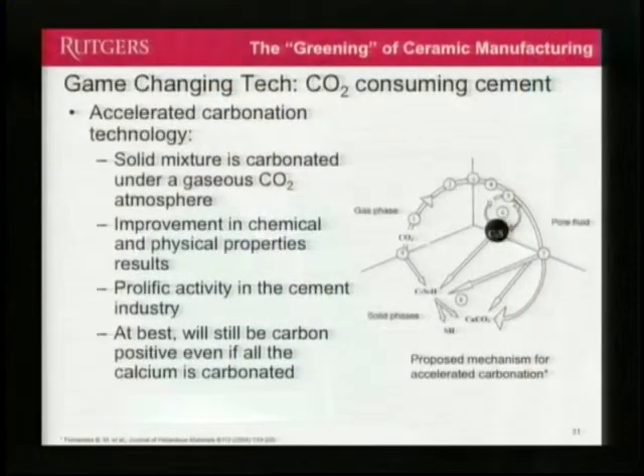And then there's another area of cement where people are calling this technology accelerated carbonation, where you're basically putting CO2 in as a gas, and while the cement is curing, you're actually adding the CO2. And this is just a cartoon of the cycle for doing that. But even if you put all the CO2 back in the cement, you still have all that fuel you've spent trying to heat that cement and make it a cement. So you're only going to cut the amount of CO2 at most by a factor of 2, but not get rid of it.